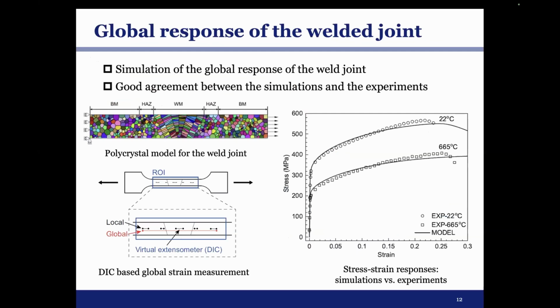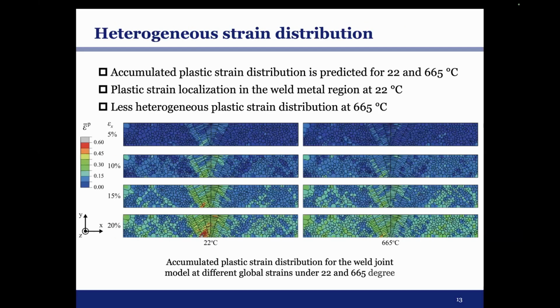So with these parameters well calibrated, our first step is to simulate the response of the whole specimen. And as we can see here, we achieve the goal. That is, there is a good agreement in terms of the stress strain curves for the whole specimen for the two temperatures. And we also calculate the distribution of accumulated plastic strain for two temperatures, and we found there is a strain localization in the middle part, that is the weld metal. However, this plastic strain distribution is more diffusive at high temperature. That is, of course, because of more viscosity at this high temperature, which is in good agreement with our experimental observation.